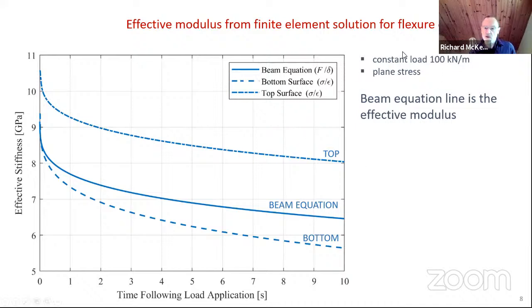For that same numerical experiment shown in the last slide, I've got a constant load of 100 kilonewtons per meter in plane stress. I've called it the effective stiffness, but that's the effective Young's modulus. It starts off at the elastic value at time 0, and then decreases over time. I've plotted three different ones. The first is based on the force and displacements at the center under the applied load, from the beam equation, and you can see that it decreases from a little over 9 GPa to about 6.5 GPa after 10 seconds. That's based on published models for freshwater ice. So it's quite significant over that time.